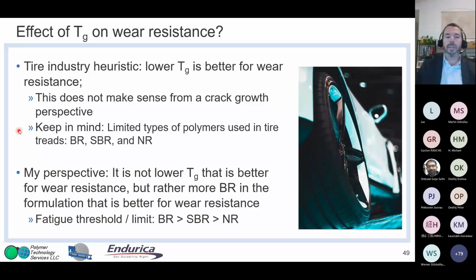But we have to remember that there's very few polymers that are actually used in tire treads. It's essentially only BR, SBR, and natural rubber. And so my perspective is, it's not lower Tg that's better for wear resistance, but rather more BR in the formulation because of this ranking of fatigue threshold. BR is higher than SBR, which is higher than natural rubber. And BR is about twice the fatigue threshold of natural rubber.